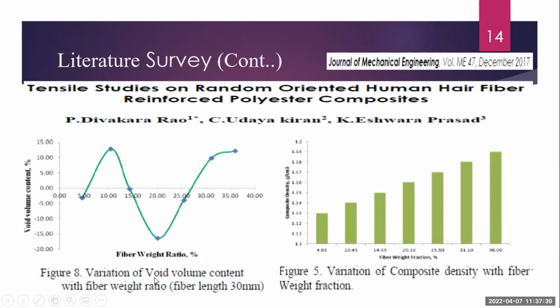They also found the presence of void volume content in the fiber weight ratios. You can see that at 5% to 10% the void percentage is increasing, but when we increase the fiber weight percentage in the polymer, the void percentage decreases very drastically. But when we increase the weight percent of the fiber in the polymer to more than 20%, the void percentage increases again. Got it? And again, they found the density. They concluded that as the fiber percentage in the polymer increases, the density of the composite will also increase simultaneously.